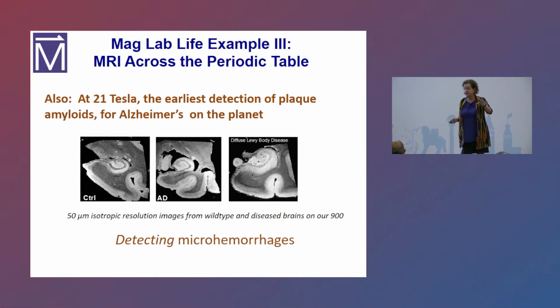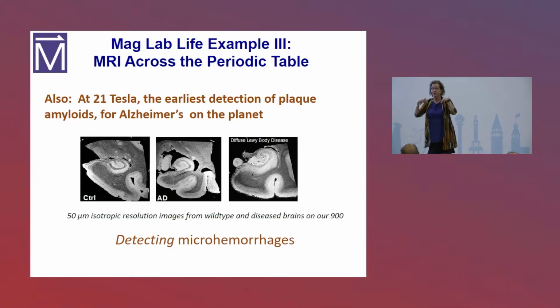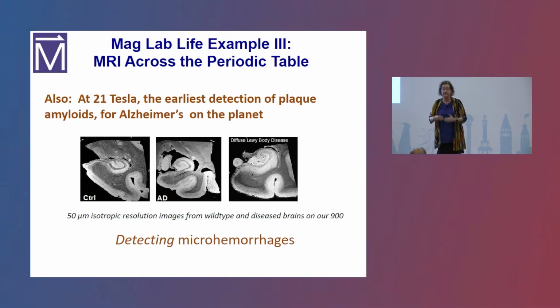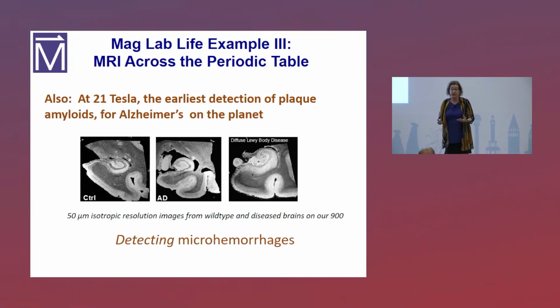We can't do it with human brains yet. These are still rat brains and small animal brains. The biggest diameter is about this much for this in vivo work. But what happens is that when the plaques form, they create microhemorrhages. And boy, when you do MRI, that's what you can see, right? When you do MRI, you pick up the hydrogen. I don't know if you know this, but you're looking at protons in the hydrogen, and that's what you're imaging. And if you increase the field, you have to increase the RF. It's a much higher frequency, so that is a shorter wavelength, and it gives you higher resolution.